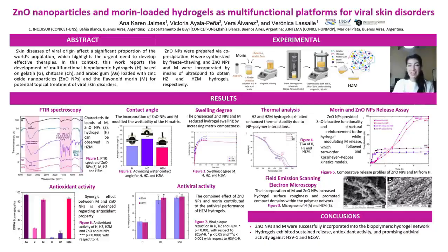Virucidal assays against herpes simplex virus type 1 and bovine coronavirus, both associated with skin infections, demonstrated promising antiviral activity. The combined incorporation of Morin and nanoparticles contributes to antiviral performance of the hydrogels, reaching very high inhibition percentages for both viruses. Finally, micrographs also showed that Morin and nanoparticles modify the hydrogel morphology, increasing surface roughness and promoting compact domains within the polymeric network.